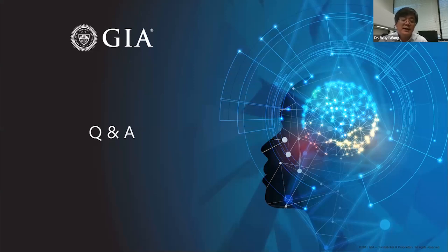Just keep in mind, it's very important, the cut contributes a lot to the face-up color of the diamond. But let's say you have two diamonds with exactly the same size and same cut. They have different tones, and the main reason for the difference is the concentration of the defects. But the concentration of the defects is very low overall, at the ppb level, or the ppm level.